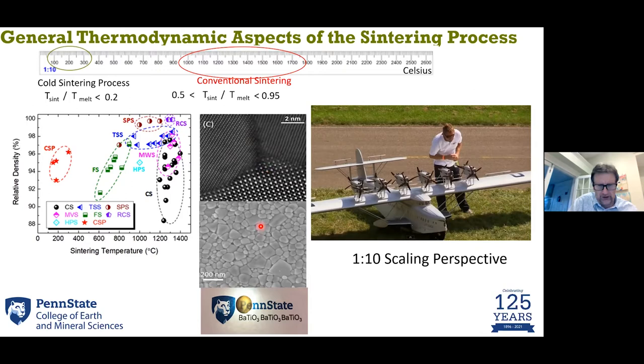and then here is all the best in class of all the other fancy techniques to sinter, including spark plasma sintering, microwave sintering, conventional sintering, etc. Cold sintering is over here, much lower temperatures and also significantly faster times. So we're looking at a 10 to 1 change in the total energy, if not greater, at least 10 to 1 in terms of that.